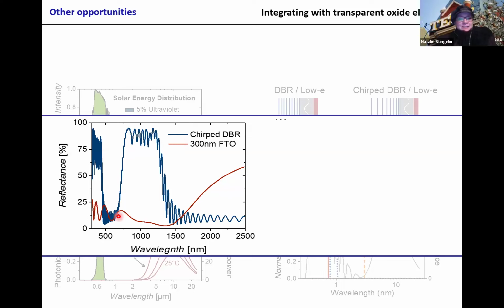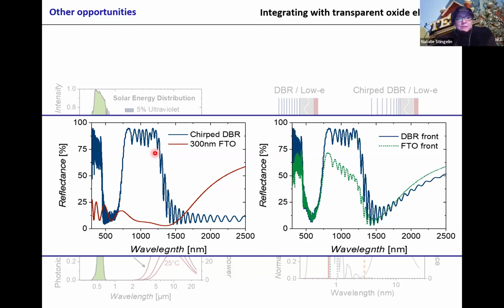The FTO here in red, you see it starts to really reflect above 2 micrometers. Now, when we put them on top of each other, you see we can get actually the performance of the DBR in blue, and we can get the reflection of the FTO. So we really get a good combination where only the 1.5 micron area has a dip.